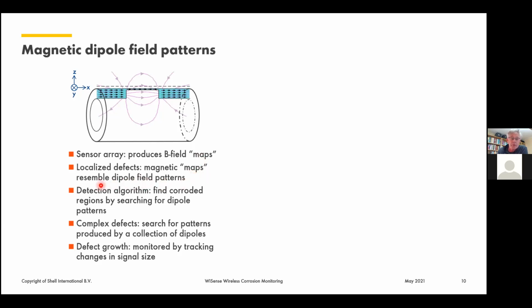And then there is a detection algorithm that finds the corroded area by searching for such a dipole pattern. And there are complex defects. If there are complex defects, then the pattern that it searches for is a collection of dipoles. And then there is a defect growth analysis package. So there's a detection package and a defect growth package, and I'll come back to that. That is monitoring by tracking changes in the signal size. It's detecting the growth.